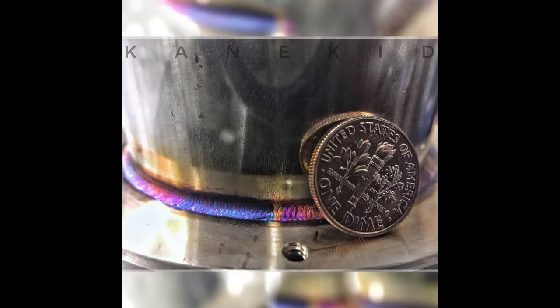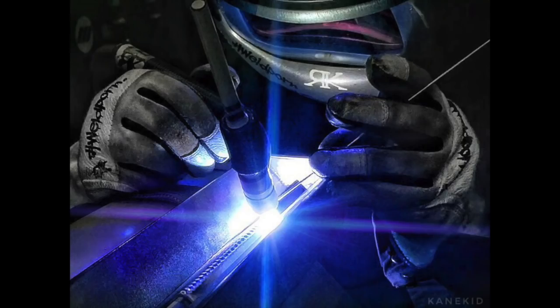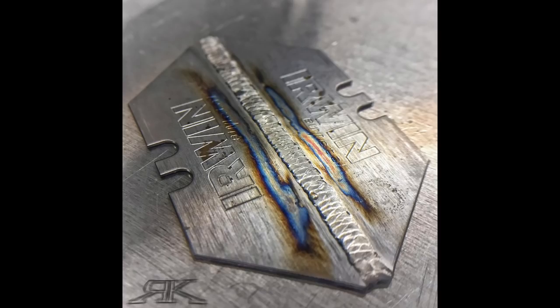Mm-hmm. If not, then I'll take a piece of Scotch-Brite, or the toothbrush style stainless steel brushes, and run those along where I'm going to weld. Remove that, acetone it, fit it up, and ready to go. A lot of the stainless steel I weld is a 4B finish, and it comes with a plastic protective sheet on it. A lot of times, I just peel back the plastic, and if it's old, it has a thick residue. But if not, then I usually just go with it and see how it goes.